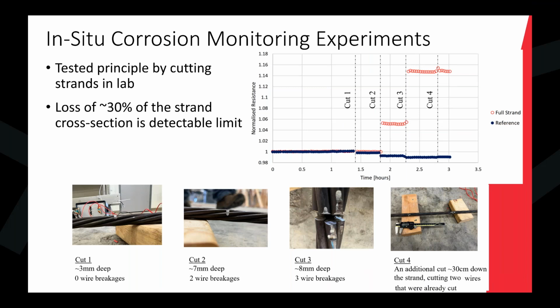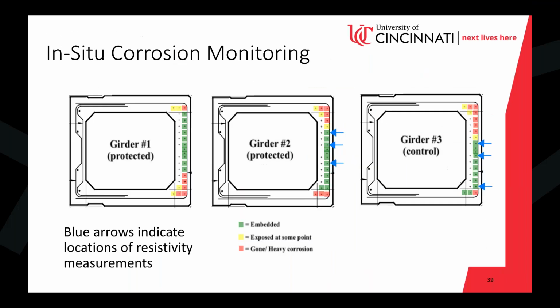So what we're expecting with the resistance is when we lose about 30% of the corrosion cross section of the strand, we should hopefully be able to see that and know that the strand is undergoing corrosion that might eventually completely separate it mechanically. So this is mechanical. Before we set up the monitoring system, it gave us some confidence that we would be able to make a measurement. What we did is we set this up on 6 different strands that were embedded in the girder.